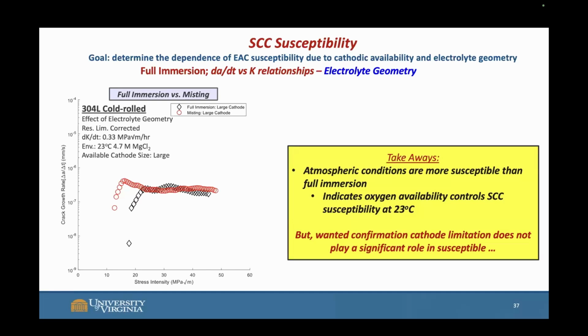So then we can move on to the misting versus the full immersion testing that we've done. We originally did it at 23C with that large cathode sample. So only that front part was painted. The rest of it was available for testing, and the cathode size is then only going to be limited by the electrolyte or the misting conditions. We did find, though, at 23C that atmospheric conditions were more susceptible than our full immersion. And so this would indicate that oxygen availability is what is causing that increase in stress corrosion cracking. But we did want to just confirm that this was right.